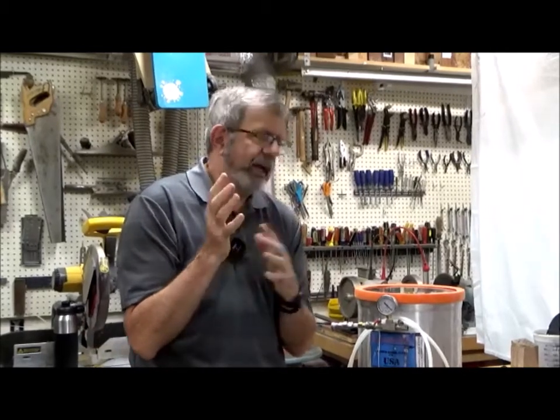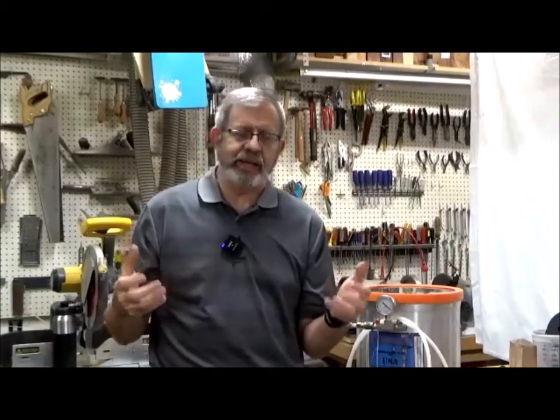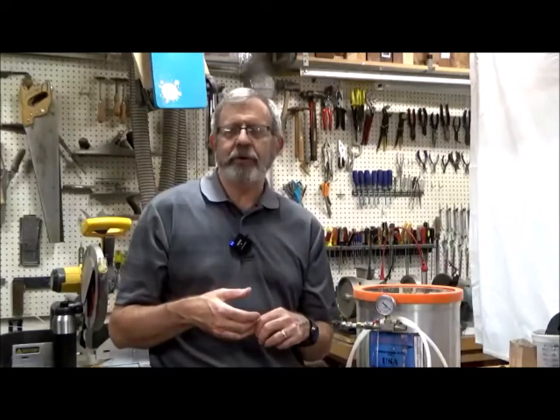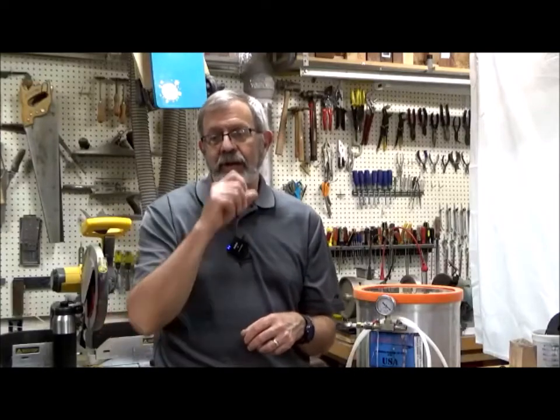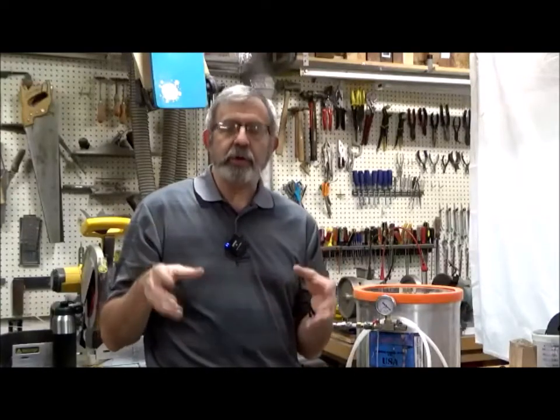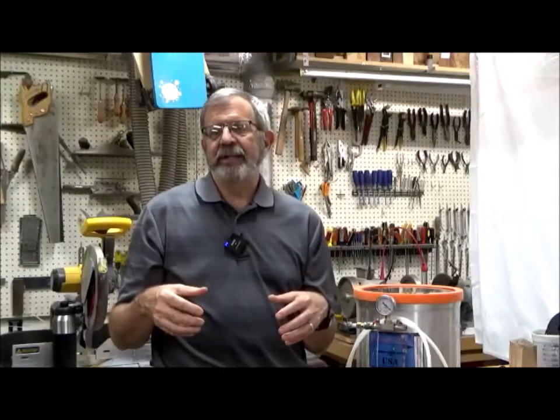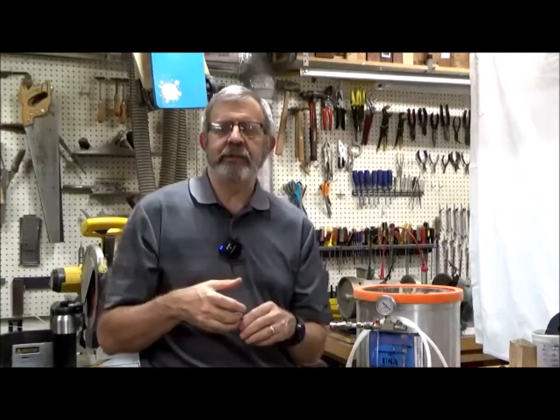You need to start out with it dry. I was talking about if you do have a bowl blank, the first time I did this, I had this nice 12-inch bowl blank, about 4 inches thick, really nice spalted wood. And I put it in there and I realized that it used a half a gallon of resin for this piece of wood, that's $40 worth of resin. And then I ended up turning out the inside of the bowl and turned $20 of that resin away. So if you aren't going to core the piece, rough out your blank first, and then cast it, then put it in the vacuum chamber and stabilize it. But it is not economical at all, unless you have such an incredible piece of wood, to stabilize just whole bowl blanks. It just doesn't make sense to do that.